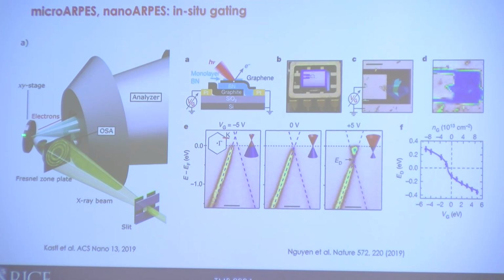And these, together with what's known as the deflector mode... in the past we had to rotate the sample relative to the analyzer to map the entire Fermi surface. But as you can imagine, if you have a tiny sample and you rotate it, your beam is going to walk on your sample and then you're going to lose the sample. But there's been development of what's called the deflector mode. Basically, you can use electrical deflectors without moving anything, just making sure that you're measuring different slices across this emission angle. And these two things together really enable the measurement of tiny, tiny samples.